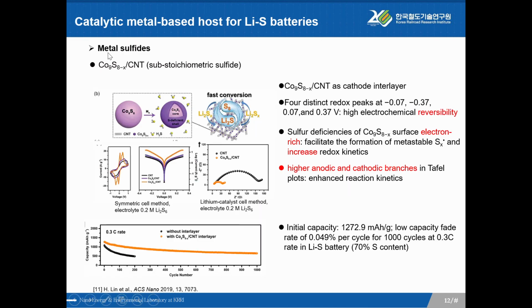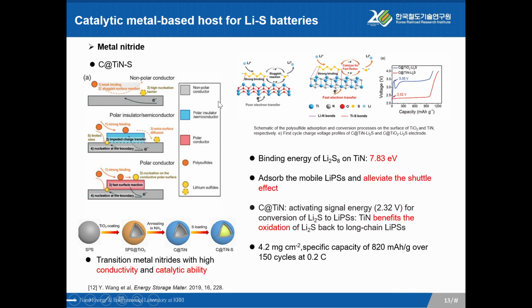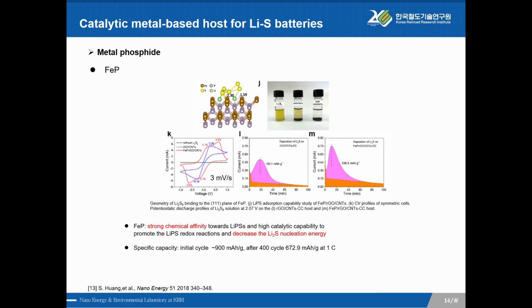This is another metal sulfide. Also, we can see there is a high current density and high exchange current and faster charge transfer. This is metal nitride. We can see that there is a large bonding energy between catalyst and lithium polysulfide. All the catalysts are according to the requirement: polar to polar interaction or Lewis acid to Lewis base interaction. Yeah. This is metal phosphide.